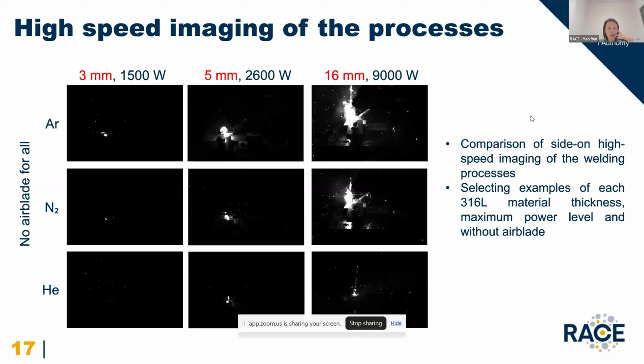And here, the high-speed camera captured the spatter and plume generated. This is a really nice comparison. We can see that with increasing thickness, there is more spatter and really strong plume generated. And if we compare vertically, we can see that for the thicker section, helium did give a really peaceful process compared to argon. That's really a nice result for comparing the processes.